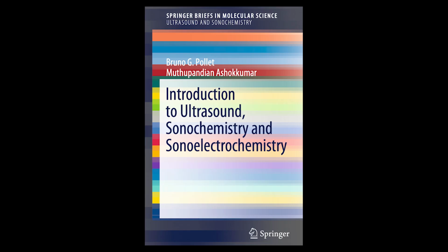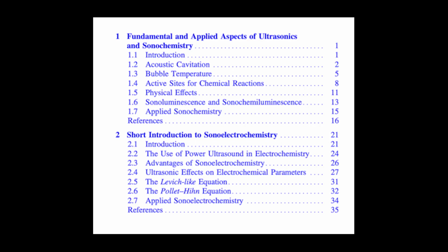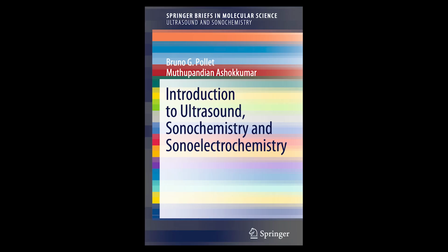A jet of liquid shooting out. Shooting inwards, typically directed right at the nearby surface, and the speeds are incredible. The source says up to 200 meters per second. Wow, that's like bullet speed almost. It's extremely fast for a liquid jet at that scale. And this intense, localized bombardment is what causes severe erosion, fragmentation of particles, surface pitting, and it's also fantastic for cleaning surfaces. It literally sandblasts things at a microscopic level. We'll come back to that cleaning effect in electrochemistry.